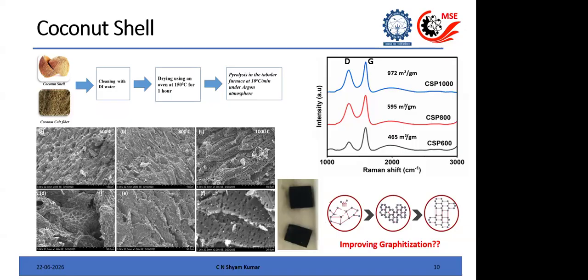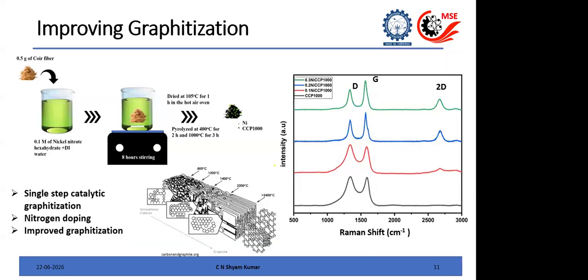So now the question is how to increase the graphitic content. One way, as I told, is to increase the temperature, but that won't help all the time because you don't have very good furnaces that can go to that temperature. So another way is that you can use a catalyst. This is what we are trying to do with catalytic graphitization. You facilitate the conversion from sp3 to sp2 through a catalyst. That way you can increase the sp2 content so that you don't have to go to a very high temperature. Within our furnace itself, we can do this.